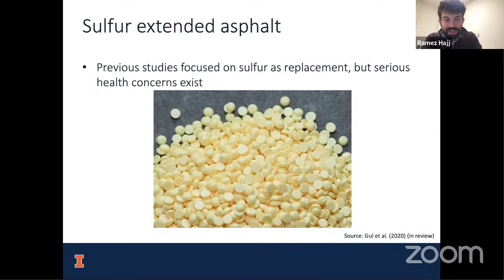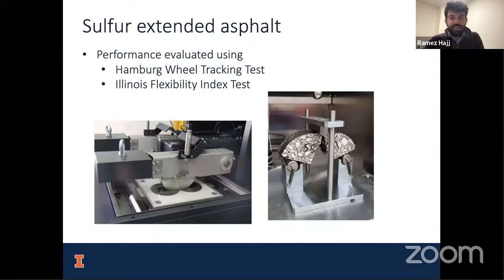But we needed, of course, to check if the performance is as good. Because one issue with sustainability is that if the performance is not as good, the technology is not sustainable because you have to do reconstruction or rehabilitation so quickly. So if you don't have a good performance, you can forget about using that as a replacement technology. It needs to be at least as good as the asphalt mixture. So in this case, we evaluated sulfur extended asphalt mixtures using two tests.